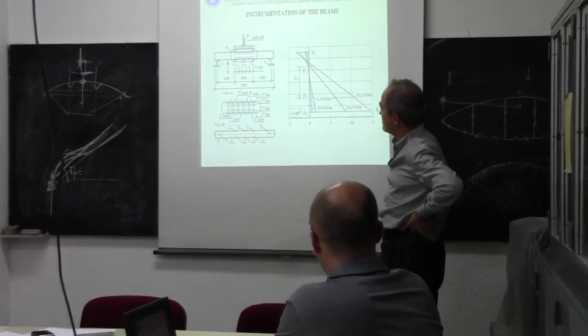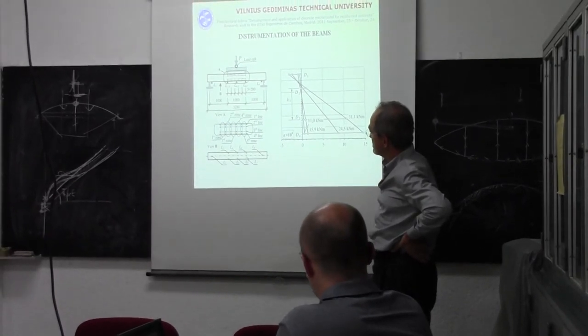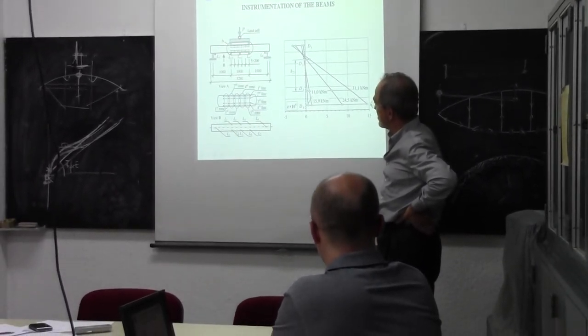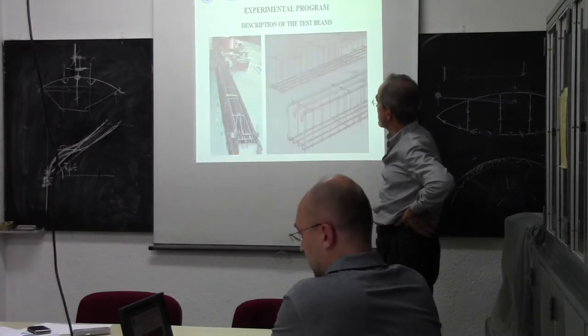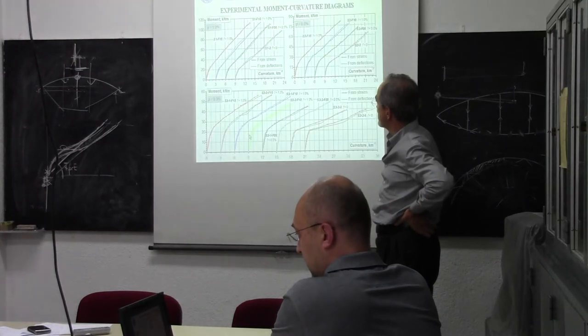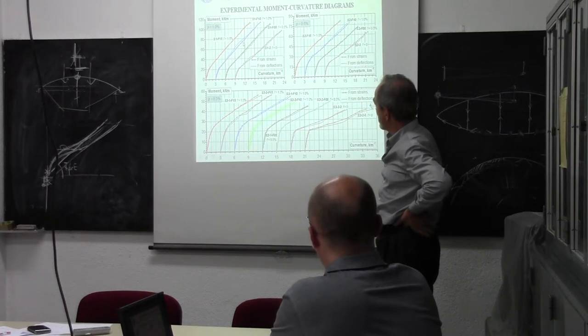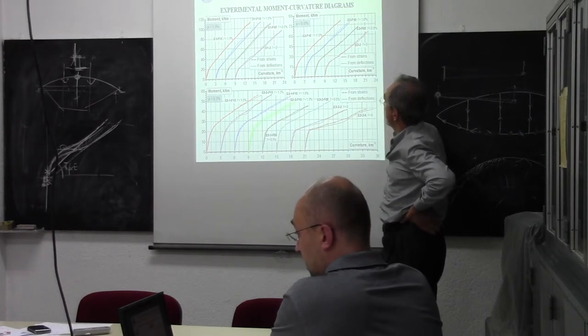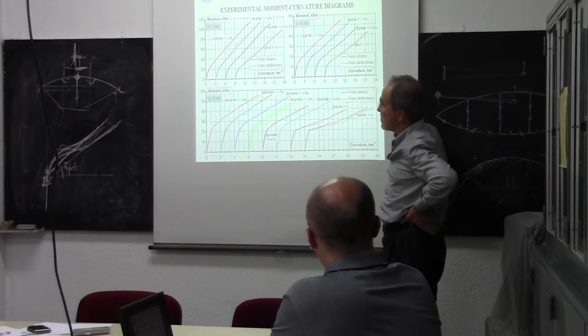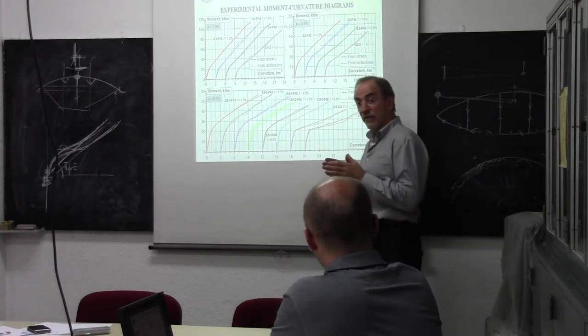It was 8 linear transducers, inductive transducers. And then we obtained two types of diagrams. Dotted diagrams obtained from strain measurements, and dashed lines obtained from deflection measurements. So you measure deflections? Yes.